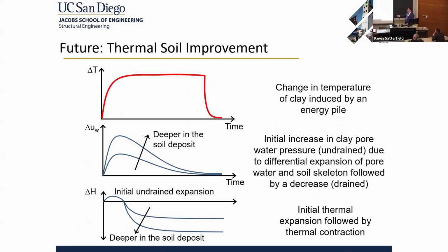While the soil is being heated, it's going to increase in pressure due to this differential thermal expansion. And we've done some studies that show the deeper you go in the soil profile, the higher your pore pressure is going to be. And initially, you're going to have some thermal expansion when the soil is completely undrained. But as these pore pressures dissipate and move away to other regions, you're going to have thermal contraction. And that thermal contraction is going to lead to a decrease in void ratio and an increase in shear strength.